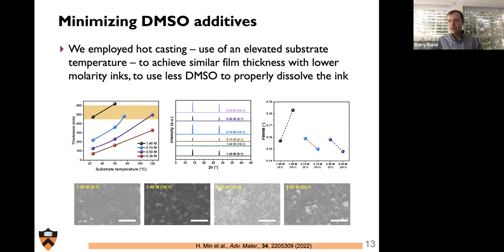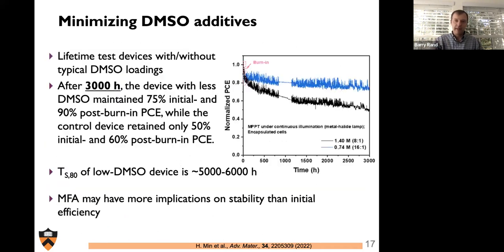So obviously that structure is not entirely commercializable, but it's also very archetypical in that we can make pretty facile comparisons of things like stability to what's pretty well established in literature. And what's pretty well established in literature is a device kind of like this. This hits 50% of its stabilized efficiency around 4,000 to 5,000 hours. And that's relatively typical, if not a bit better than typical. I should note that this is a 3,000 hours device.